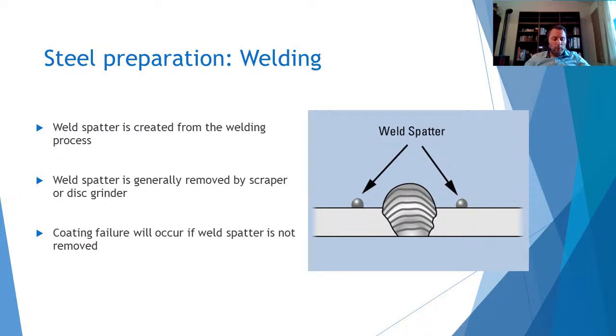The preparation of welds is very important too. Welds generally present rough, discontinuous areas on a plane surface and may have many sharp edges. Too frequently, welds are not cleaned properly, leaving weld spatter, slag, and acid flux. If these imperfections are not removed, corrosion may be encouraged. Weld spatter is generally removed by scraper or disc grinder. However, this is not always advisable without consulting a structural engineer. Coating failure will occur if weld spatter is not removed. Further, welds are often tested for cracks with a chemical test solution, a dye penetrant solution, that leaves contamination on the surface. Coating applied over this type of surface will not bond well, and coating failure with subsequent corrosion is likely to occur. It is important to remove all traces of this solution.